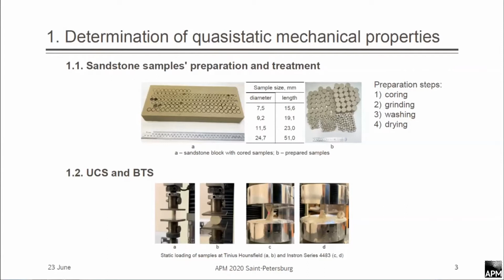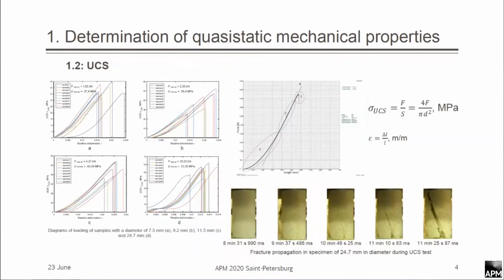And also we wanted to apply the Brazilian method for tensile strength determination. For each diameter of samples, we did 9 experiments. Firstly, we studied samples on standard rigs such as Tinius, Hounsfield and Instron. While increasing the diameter, there was an increase in uniaxial compressive strength. You might see here that while increasing the diameter from 7.5, 9.2, 11.5, to 24.7, the compressive strength increases: 38, 43, 53. Basically, we found a classic stress-strain curve